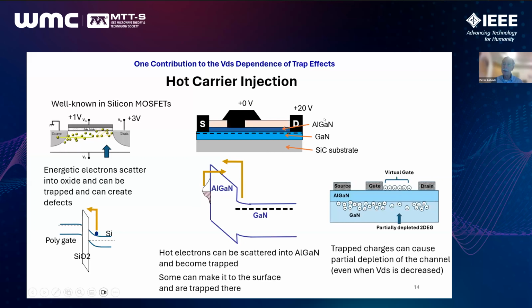A similar effect occurs in nitride FETs. If you have 20 volts on the drain, then you expect the electrons traversing the gate to drain region to pick up enough energy so that they can scatter into the AlGaN and trap there, or perhaps make it to the surface and be trapped, from which they then tend to compensate the charge in the channel, modulating its carrier density and leading to excess resistance. They stay there for a significant length of time.